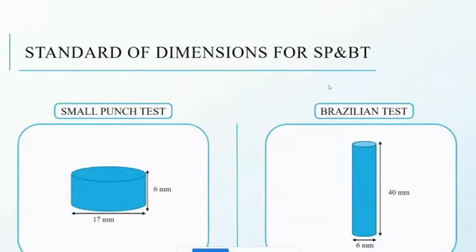So for the testing, we used a small punch test with the standard sample. It's around 6 millimeter in height and 17 millimeter in width. For the Brazilian test or the diametral test, the sample will be around 40 millimeter long and 6 millimeter in diameter.